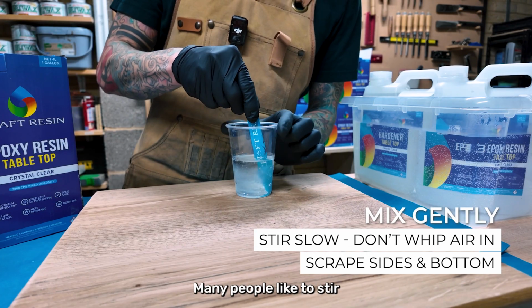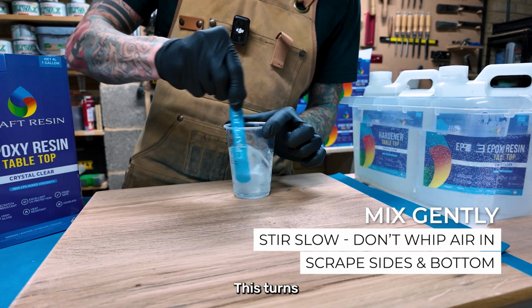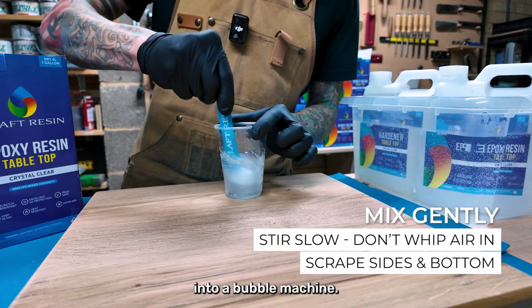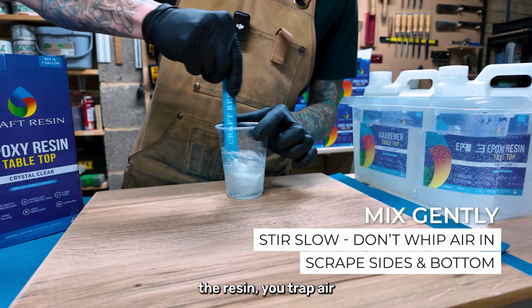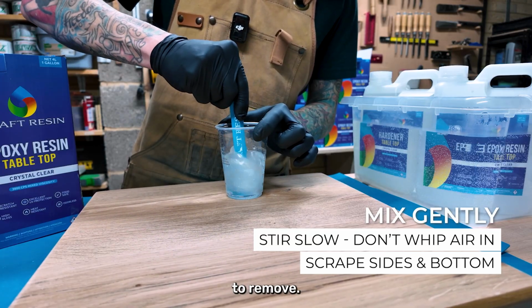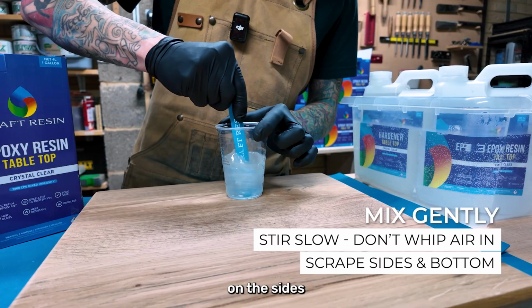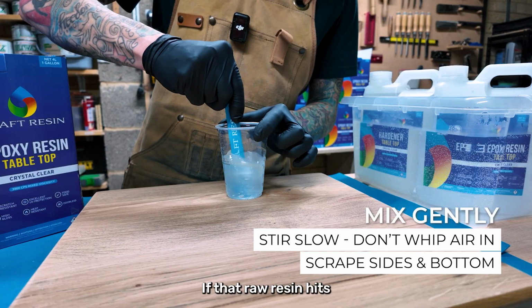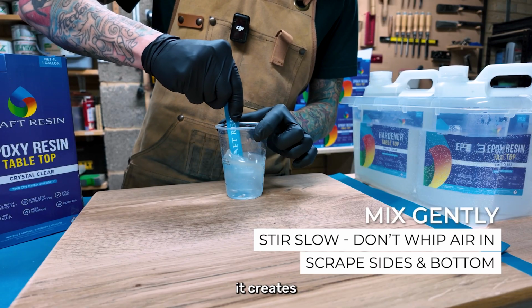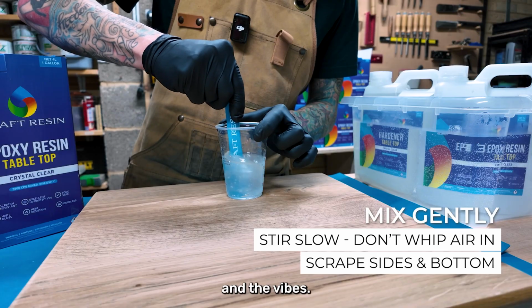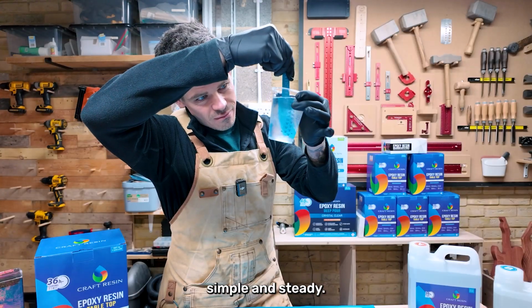Many people like to stir like they are whisking eggs. This turns your clear coat into a bubble machine. If you whip the resin, you trap air that is impossible to remove. Unmixed material also loves to hide on the sides and the bottom of your cup. If that raw resin hits your project, it creates sticky streaks that ruin the surface and the vibes. The fix is simple and steady.